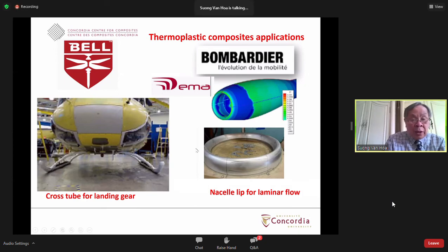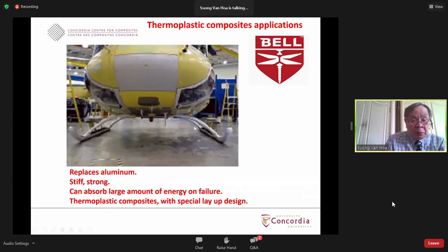For the crosspiece for the landing gear, right now it's made of aluminum, and people want to replace aluminum; there are many reasons for this. The requirement is that it had to be stiff and strong, but the challenge is also how to absorb a large amount of energy on failure. We know composites are stiff and strong, that's fine, but composites usually tend to be brittle. So how do you make sure that it can exhibit a large amount of energy absorption before failure? Here we use thermoplastic composite because it tends to be better than thermoset in terms of energy absorption. Also, we have to design a special layup in such a way that you can really have a large amount of energy absorption.